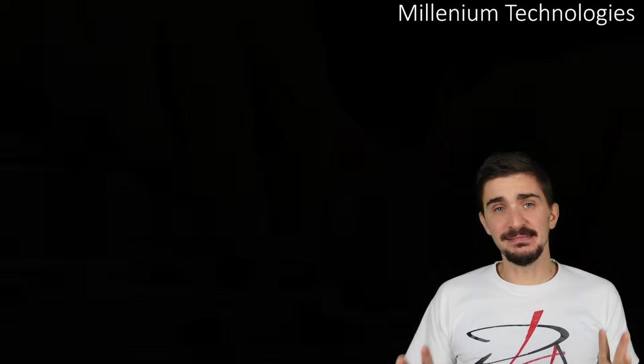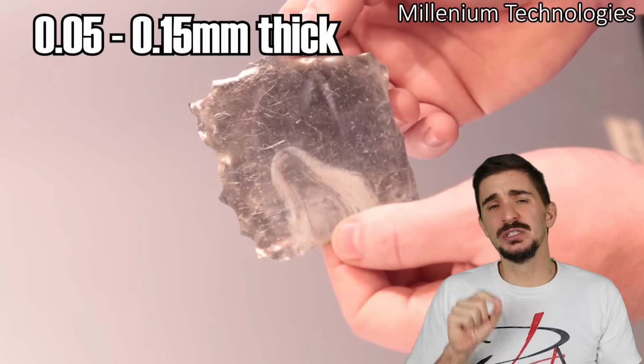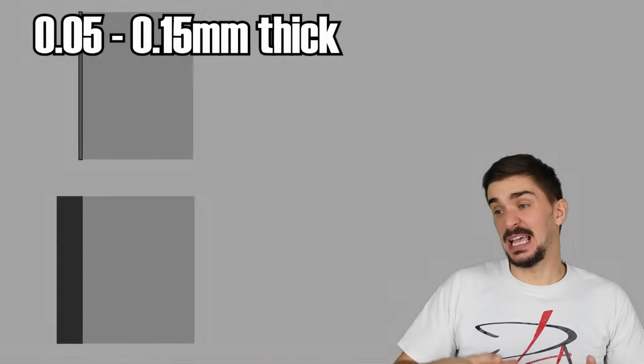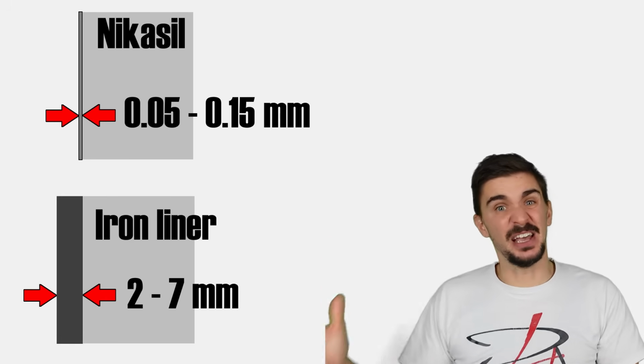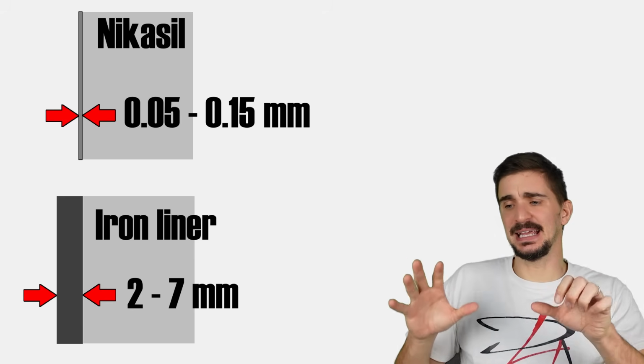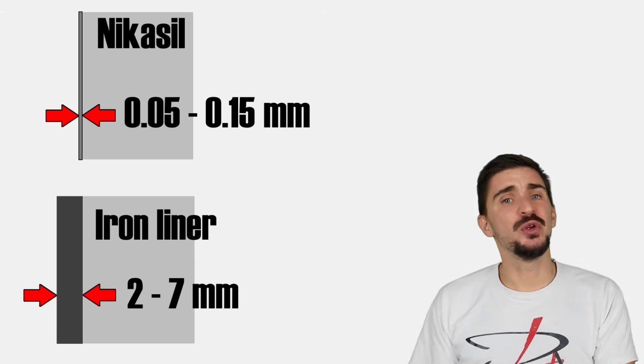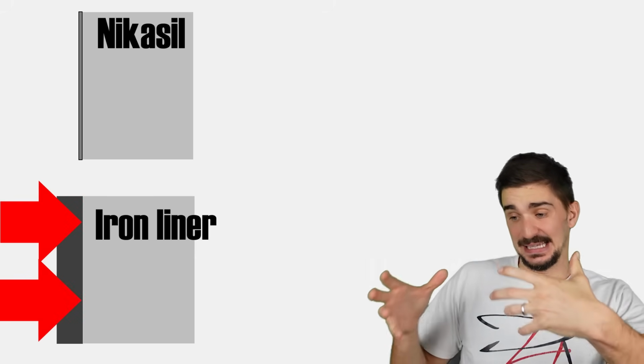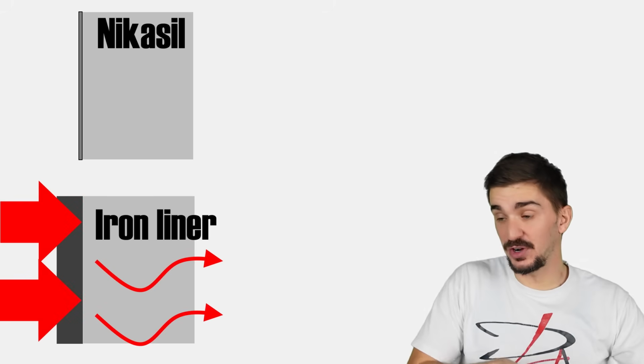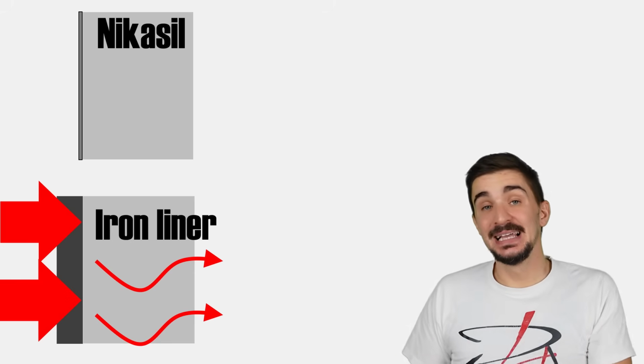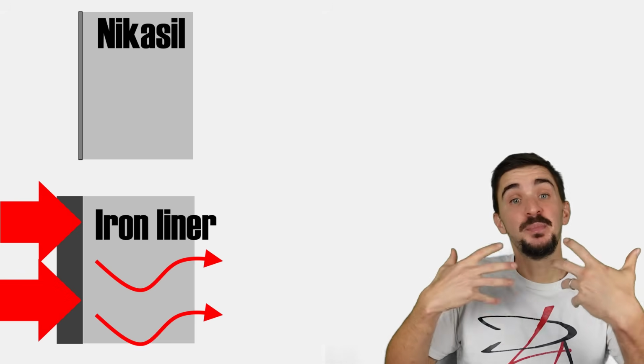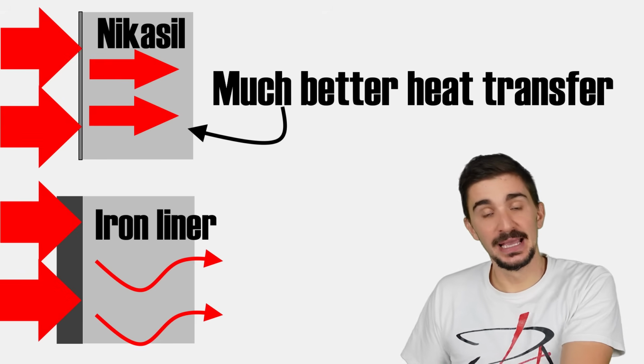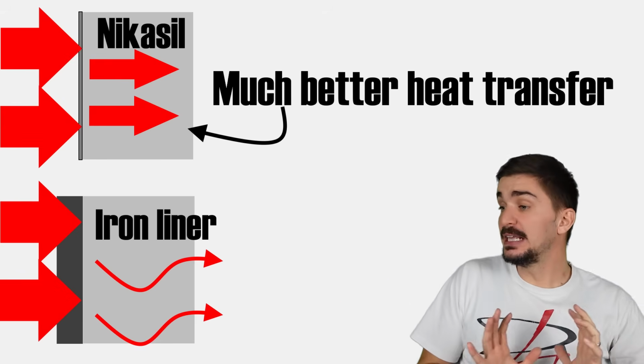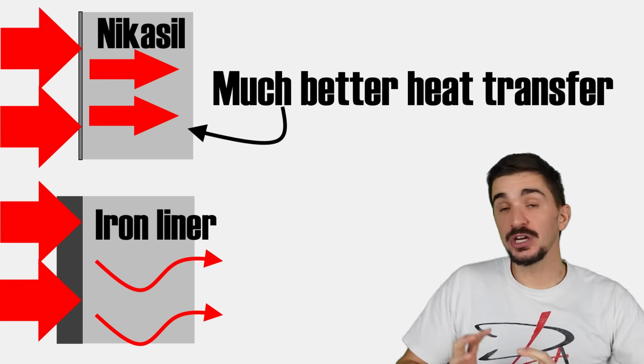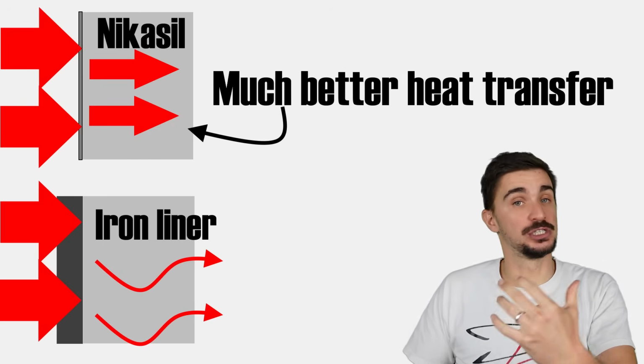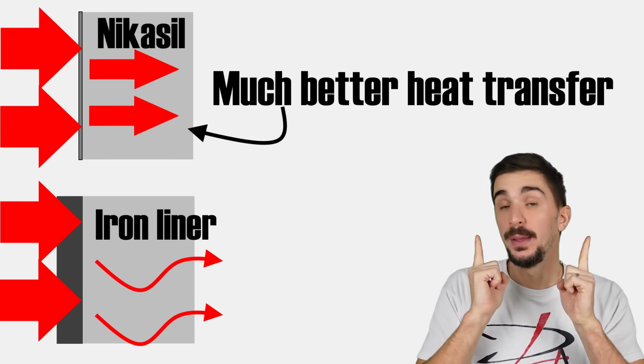Number one, Nikasil is anywhere between 0.05 to 0.15 millimeters thick, whereas a cast iron sleeve is anywhere between 2 to 7 millimeters thick. And that means that a cast iron sleeve is essentially a barrier to heat transfer, because cast iron is a lot worse at heat transfer and heat dissipation compared to aluminum. The much thinner Nikasil coating is better at heat dissipation and heat transfer. And because we have that, we can push our engine into higher combustion pressures and higher combustion temperatures without overheating or straining the engine, and that means more performance.